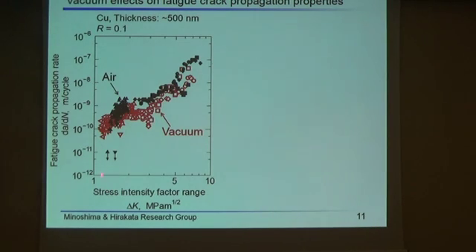This is the relationship between fatigue crack propagation rate, da/dN, and stress intensity factor range, delta K, in air and vacuum environments. In both environments, three trends were observed: accelerated da/dN, constant da/dN, and decelerated da/dN as delta K decreased. In this study, we classified these three regions into high delta K, middle delta K, and low delta K regions.